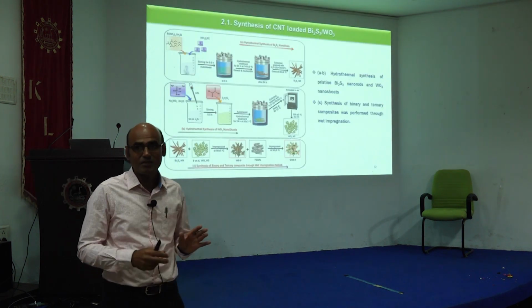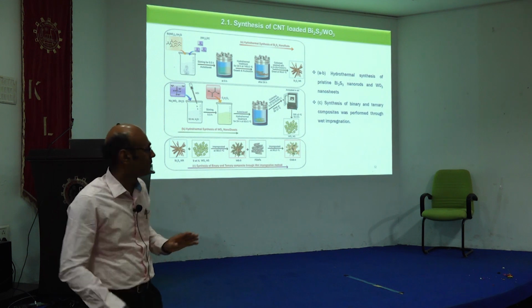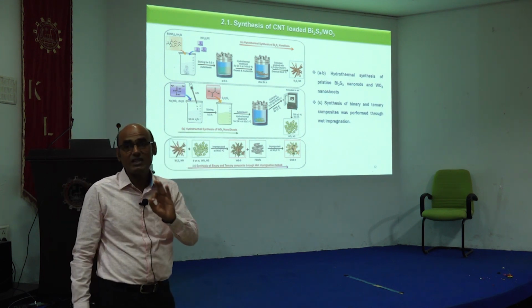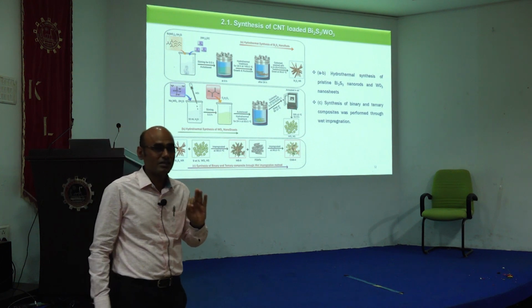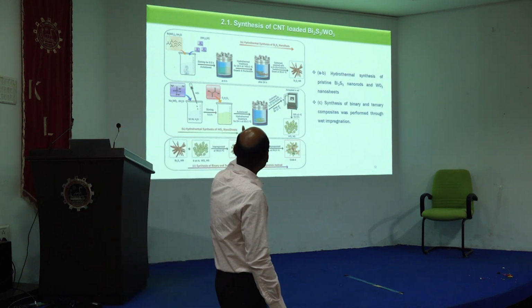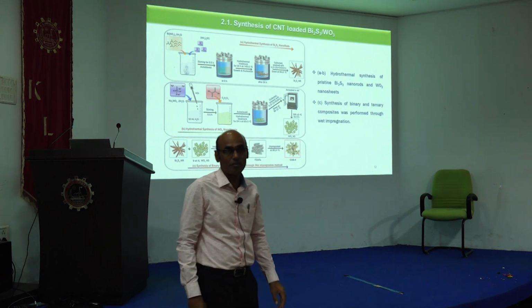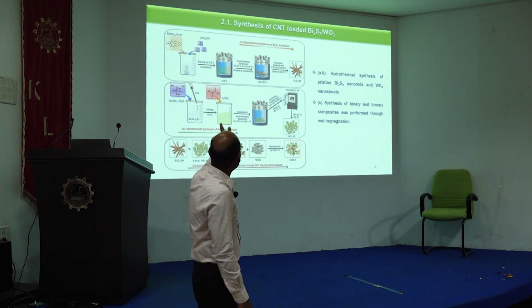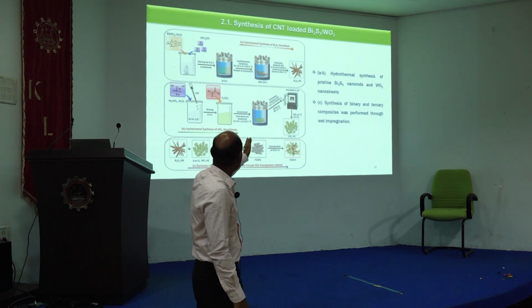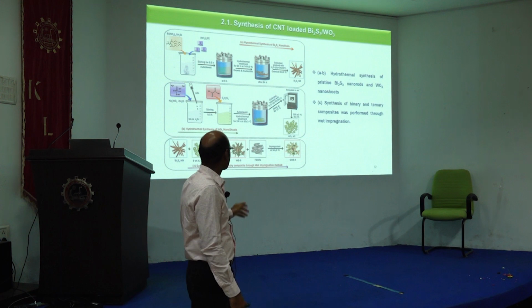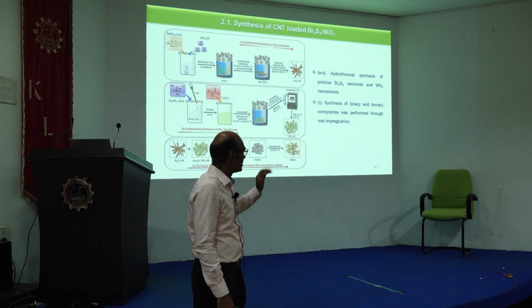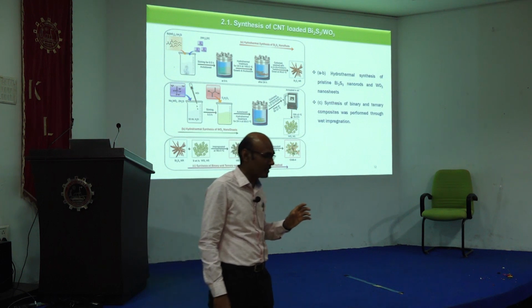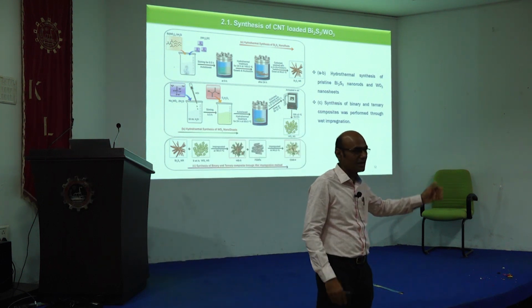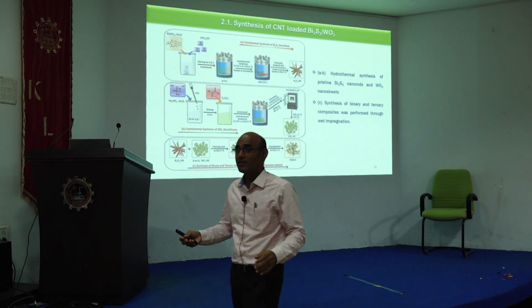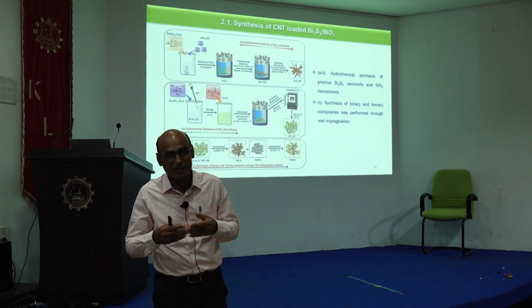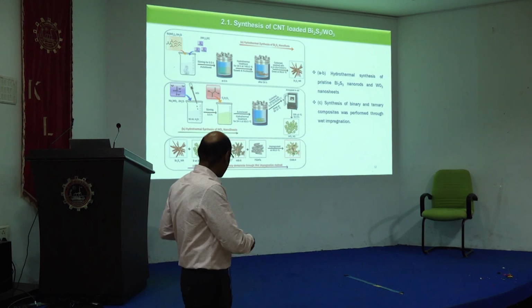So how did we synthesize it? You can get these details from the publication too. We did the synthesis as a 3-step process. The first step is the synthesis of bismuth sulfide nanorods using the hydrothermal technique. You can see various stages were involved. In the second row, you can see the synthesis of tungsten trioxide, which we synthesized separately as another material. So we prepared bismuth sulfide separately, tungsten trioxide separately, and then we integrated the two by using the wet impregnation method that we have shown here, the third one.